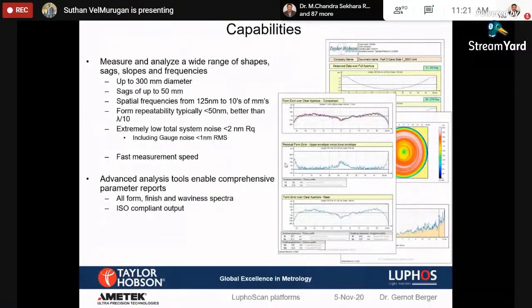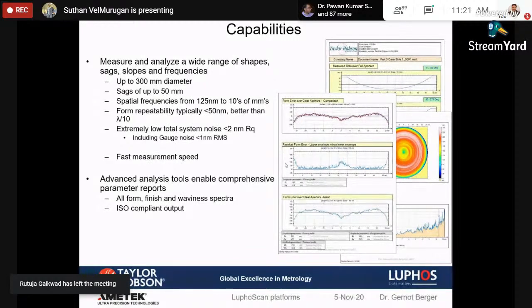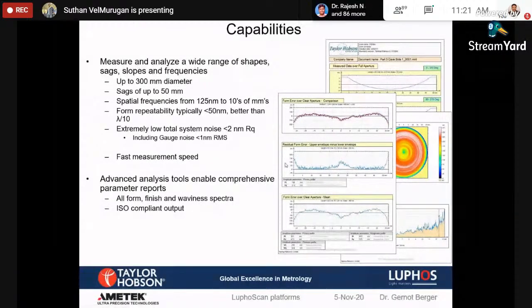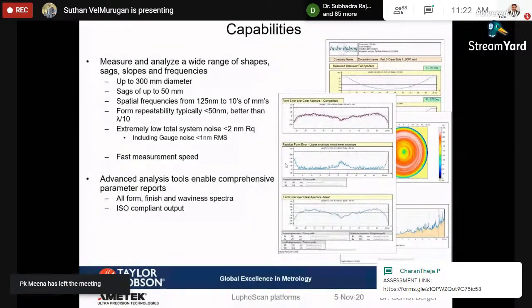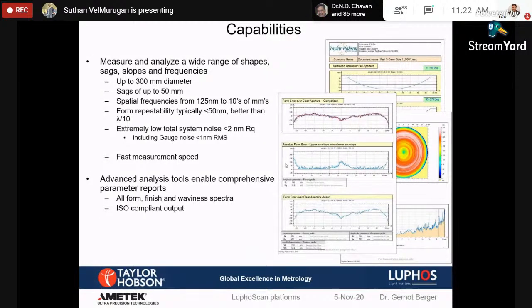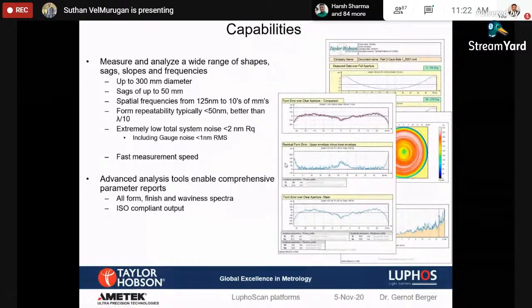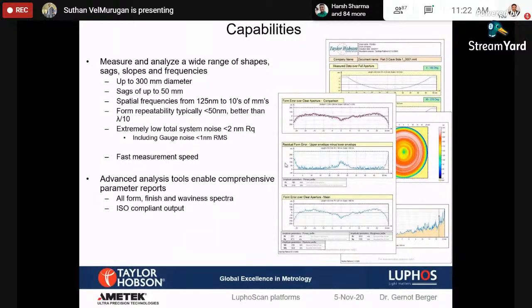Again, accuracy-wise, the capability of the machine is that we can measure up to a 300 millimeter diameter. It's a bigger diameter part. The sag, in the sense of depth, we can measure up to 50 millimeters depth. It could be concave or convex. Either profile can be measured. The spatial frequency is 125 nanometers. As I said a few minutes back, it can collect 8,000 points per millimeter. The calculation is from here. It picks up every 0.125 microns, or every 125 nanometers, 1 point in the x-axis. So in a millimeter, roughly about 8,000 points.